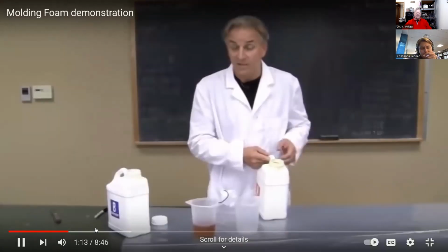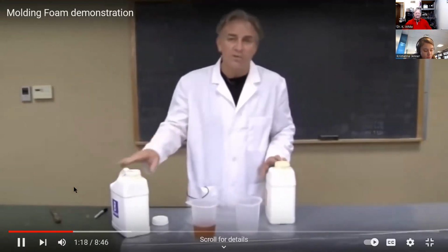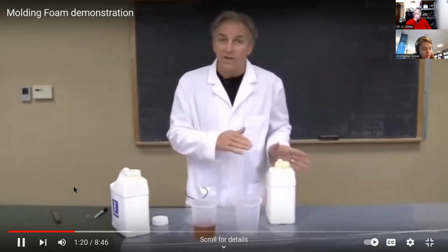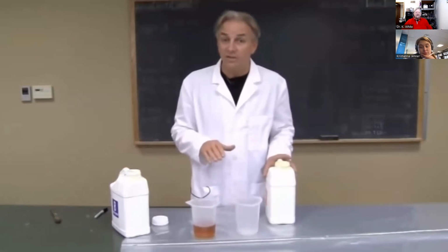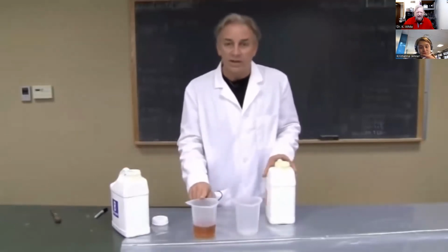Right, how this liquid foam is going to actually be mixed and used. We first conditioned our liquids to 72 degrees Fahrenheit. Best temperature to be at. Hotter means faster reaction. Colder means a slower reaction, which is going to create higher density foam. In real life, you don't do that.